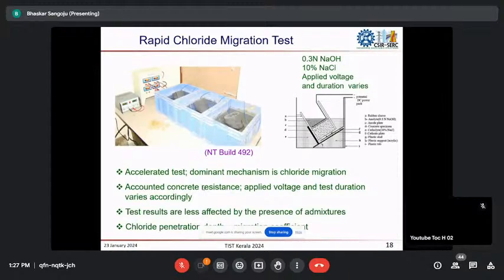And also, if any chemical admixture is present in the concrete, this will give a more reliable test when compared to the previous RCPT test. So that is why most of the researchers nowadays are using the NT Build 492 test. So here also the procedure is similar. This is the test specimen, 100 diameter by 50 thick, placed inside this inclined test setup. This is also intentionally created so that if the specimen is getting heated up, because of this inclination, the air bubbles or whatever reaction is taking place will be nullified.